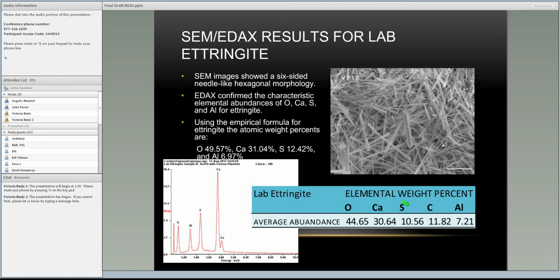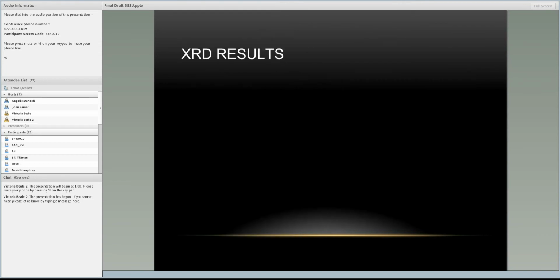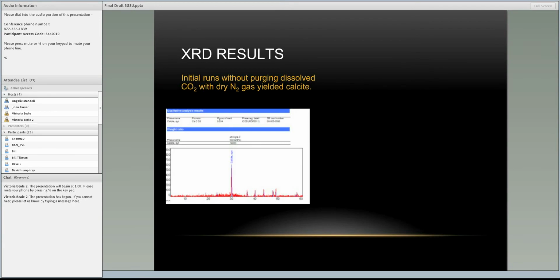And looking at the lab ettringite with XRD, this is a spectrum of the initial run without dissolving the CO2 with the nitrogen gas, and what you see is the big calcite peak in the middle there. So all we got from that run was calcite. Then when we bubbled the solution with the nitrogen gas, we got the characteristic ettringite peaks.